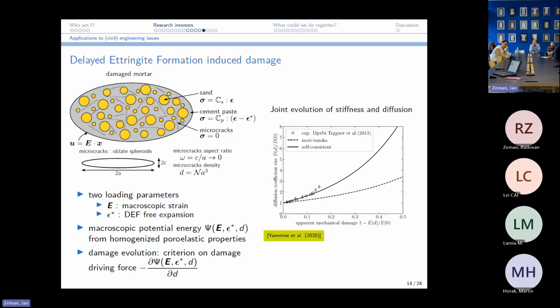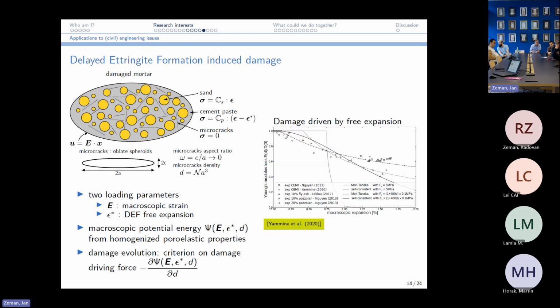And if we compare that to some experimental results we have in the lab, the increase in diffusion coefficient as a function of the apparent mechanical damage, this would be like a damage parameter in the classical, let's say, Lemaitre-Chaboche formulation. Then we retrieve trends which we have in the lab. And then we compare with measurements of the macroscopic expansion of mortars exposed to this delayed ettringite formation as a function of the loss of the Young modulus we measure in the lab. And so with that model, we could find some damage evolution law that allowed us to reproduce that.